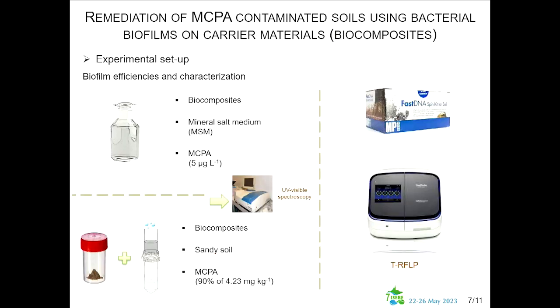After that, we can at least begin the real interesting experiment, which is to test the efficiency of the biocomposites in a liquid medium, also the mineral salt medium, and in soils, which is the aim of this procedure. So the biocomposites, modified or not, are introduced in a mineral salt medium with a concentration of MCPA at 5 micrograms per liter, or we introduce these biocomposites in a sandy soil, and we applied a concentration that is 90% of the recommended dose in agriculture.